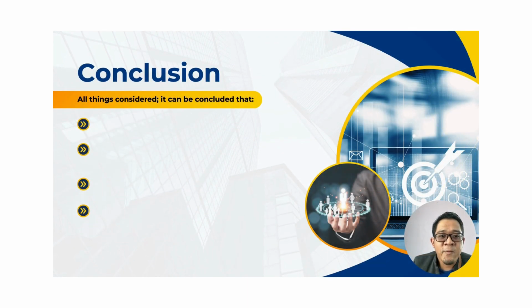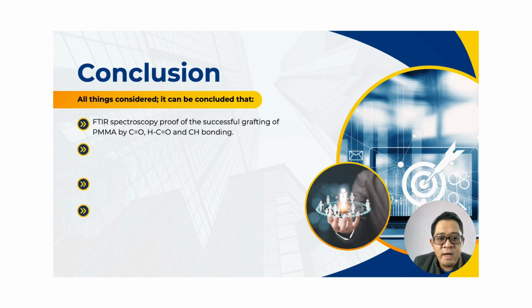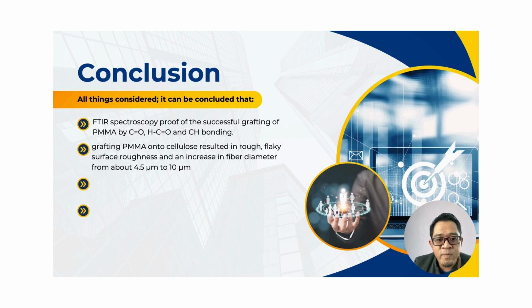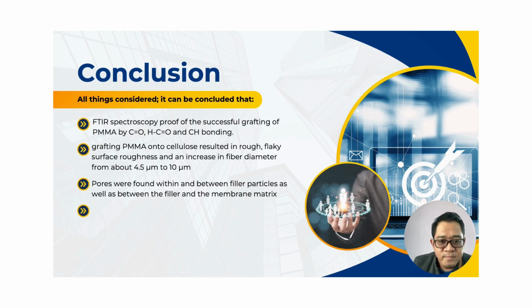And then lastly, we go through the conclusion. All things considered, it can be concluded that FTIR spectroscopy proved the successful grafting of PMMA by C double bond O, H C double bond O, and CH bonding. Next, grafting PMMA onto cellulose resulted in a rough, flaky surface and an increase in the fiber diameter from about 4.5 micrometer to 10 micrometer.